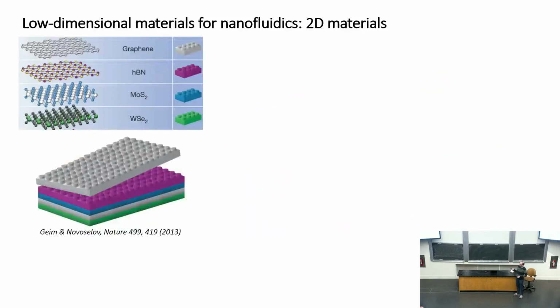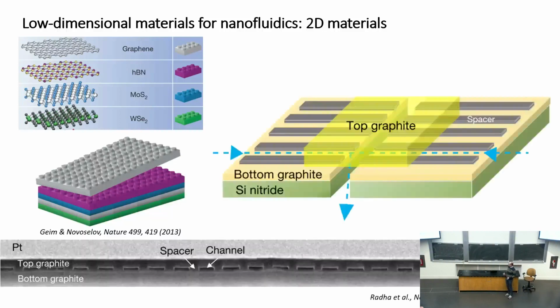Of course, something that I'm very excited about in this field is that you can take these different 2D materials and stack them. Leo knows very well how to do this, and this has enabled one really cool advance in the field, namely that you can build structures where, before you stack these Lego pieces, you etch out certain parts to make spaces. Here's a cross-section where you see a stack of graphite, graphite, graphite, and in the middle there are open spaces. These form channels for confinement.